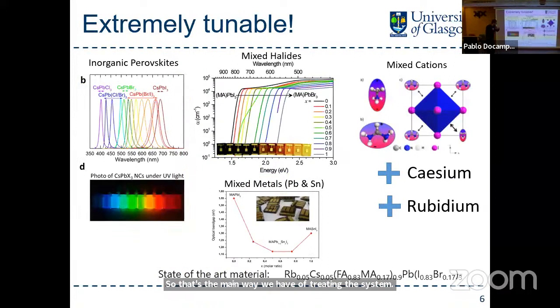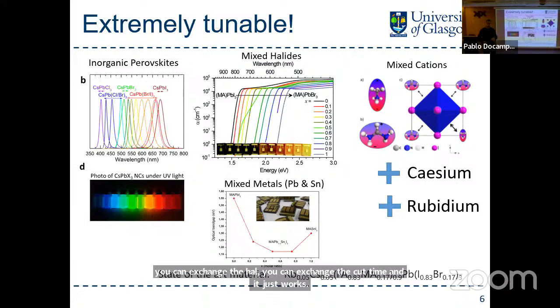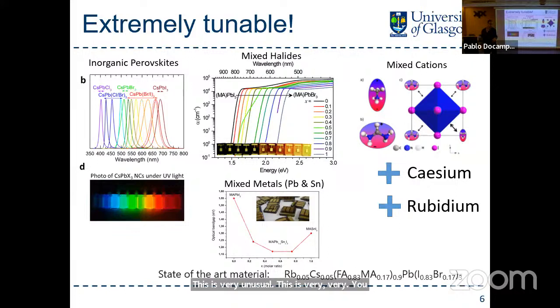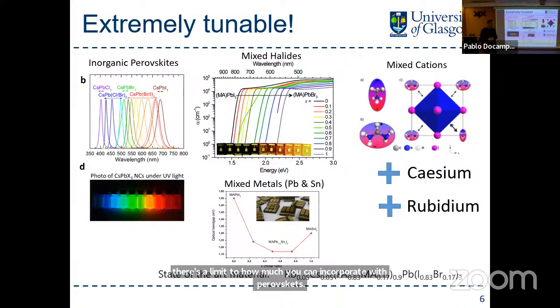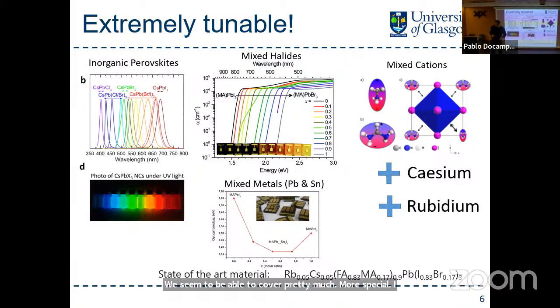So this comes out as you can basically tune it. This is some work we did on nanoparticles. You can see that you can tweak the lattice, you can exchange the halide, you can exchange the cation, and it just works. This is very unusual. This is very, very unusual. If you work in CdTe, you can change selenium for sulfur, but there's a limit to how much you can incorporate. With perovskites, we seem to be able to cover pretty much the whole spectrum, and it usually works quite well.